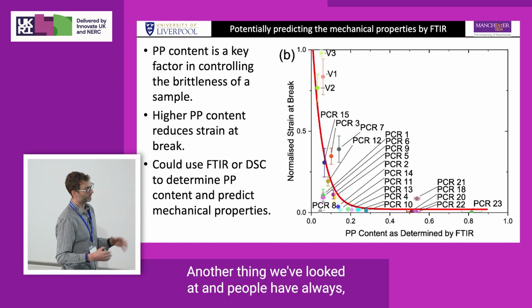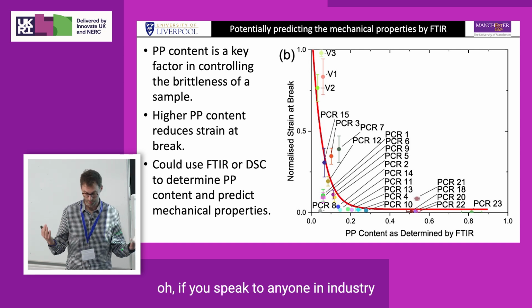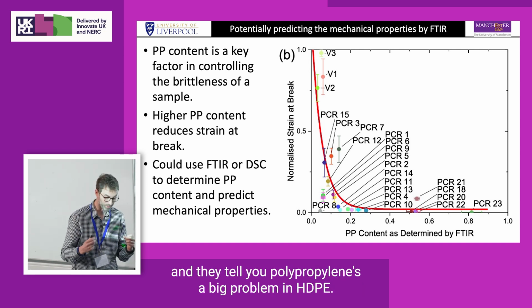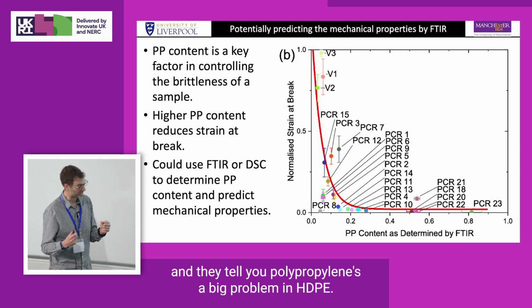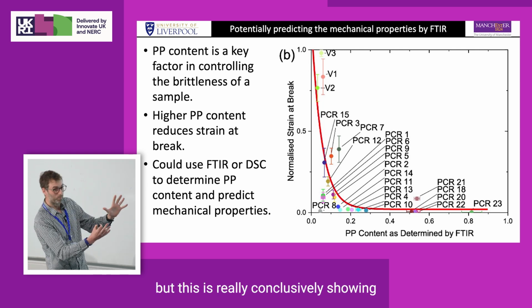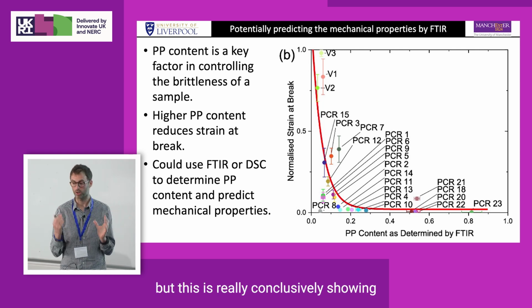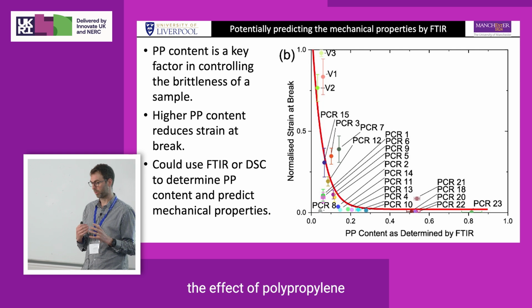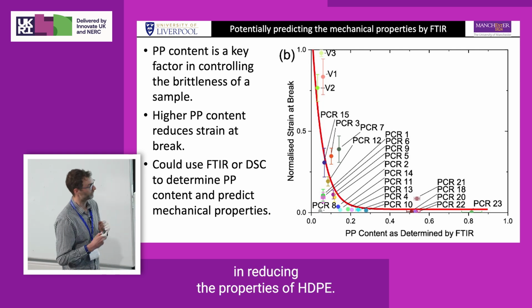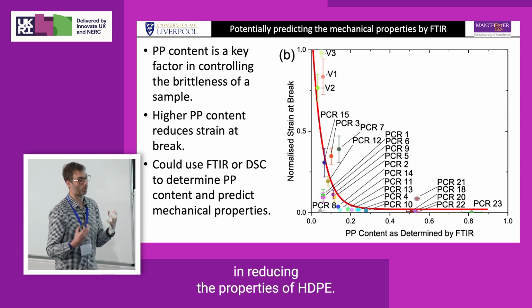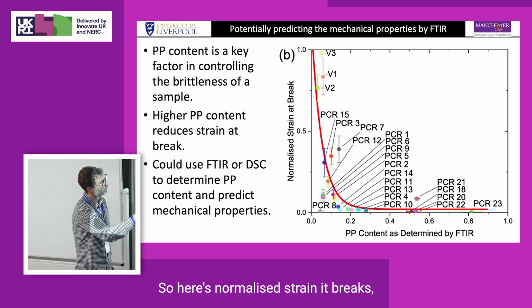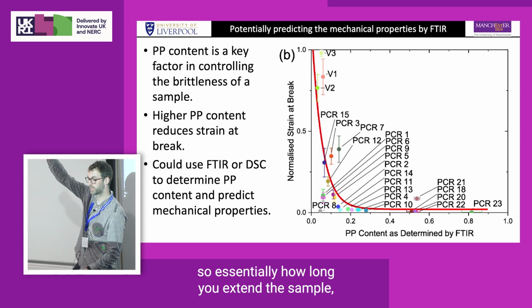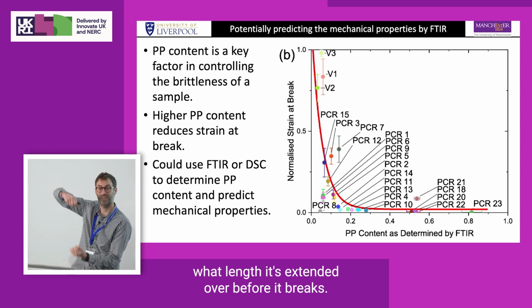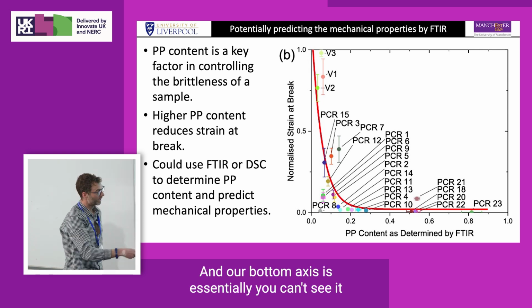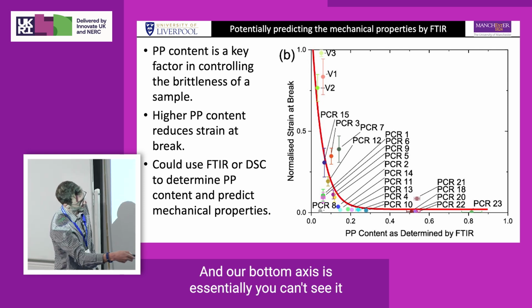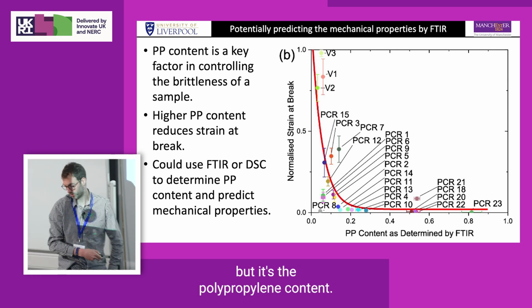Another thing we've looked at, and if you speak to anyone in industry, they tell you polypropylene is a big problem in HDPE. I mean, this isn't groundbreaking, but this is really conclusively showing the effect of polypropylene in reducing the properties of HDPE. So here's normalized strain at break, so essentially how long you extend the sample, what length it's extended over before it breaks. And our bottom axis is essentially, you can't see it, but it's the polypropylene content.